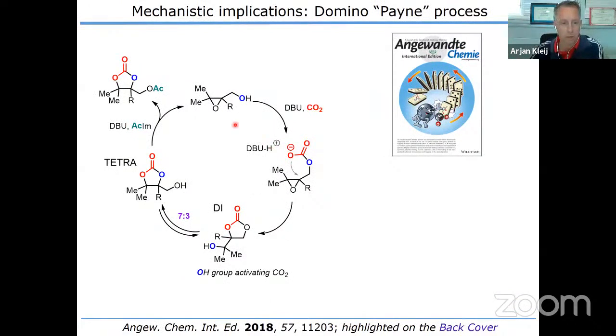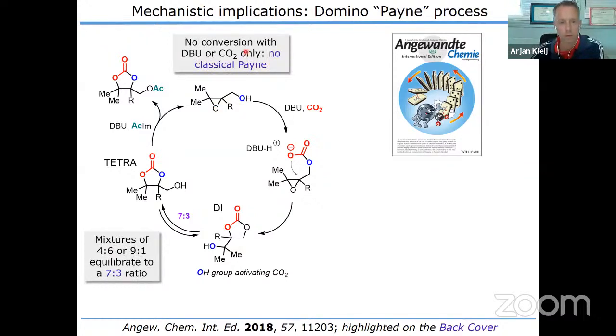Well, how does it work? If we take basically this epoxy alcohol, what we do know is that there is no conversion in the presence of only DBU or CO2, which rules out, at least from our point of view, a classical Payne isomerization of that epoxy alcohol and subsequent reaction with CO2. So we first make the carbonate, we get the carbonate to isomerize, and then we trap basically the most reactive one by using an acylating agent.